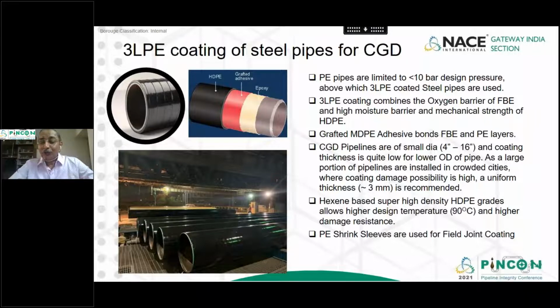CGD pipelines are of smaller diameter and the coating thickness, as it depends on the pipe OD, is quite low for low diameter pipes, as a large portion of pipelines are installed in crowded cities where coating damage possibility is high. We recommend a uniform thickness of about 3 mm for all lower sizes of pipes. Hexene-based super high density HDPE grades are now available, which allows higher design temperature of 90 degrees centigrade. Typically, this is 80 degrees centigrade as specified by ISO 21809-1, and also they provide higher damage resistance.